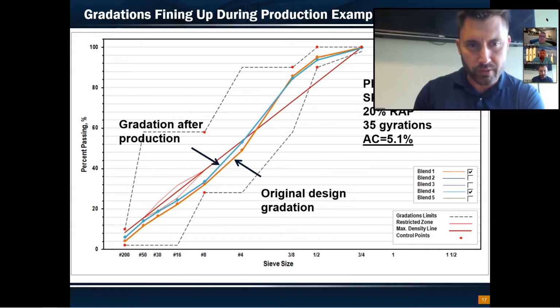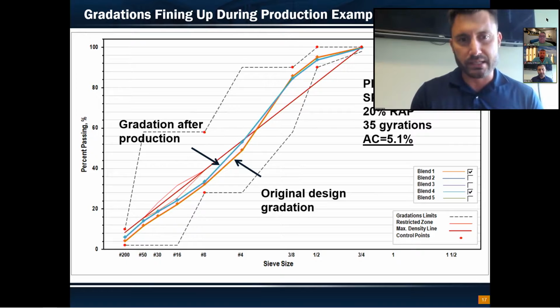That additional 0.25 is additional virgin asphalt that was added to the design. And by making these gradation changes, I've seen about another 0.25, maybe 0.3. I think Jimmy's going to talk more about that. Okay, good deal. Somewhere right around 0.5 is what we're anticipating, but about half of that is coming from reducing the recycle binder ratio.